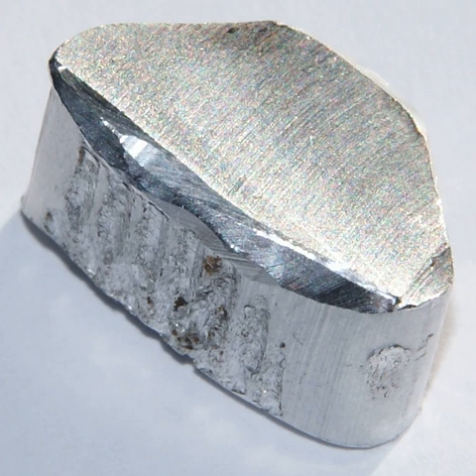Hall-Héroult process. The conversion of alumina to aluminium metal is achieved by the Hall-Héroult process. In this energy-intensive process, a solution of alumina in a molten mixture, at between 950 and 980 degrees Celsius (1740 and 1800 degrees Fahrenheit), of cryolite, Na3AlF6, with calcium fluoride is electrolyzed to produce metallic aluminium. The liquid aluminium metal sinks to the bottom of the solution and is tapped off, and usually cast into large blocks called aluminium billets for further processing.